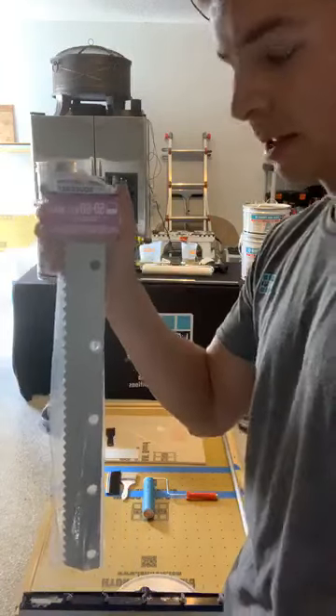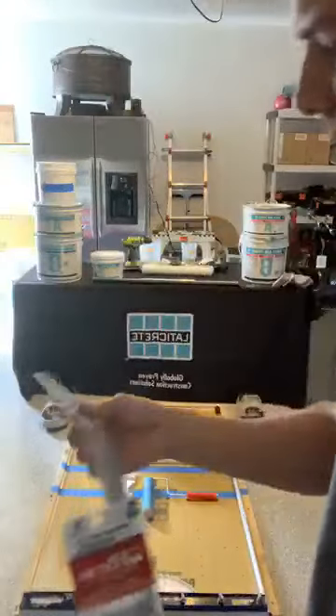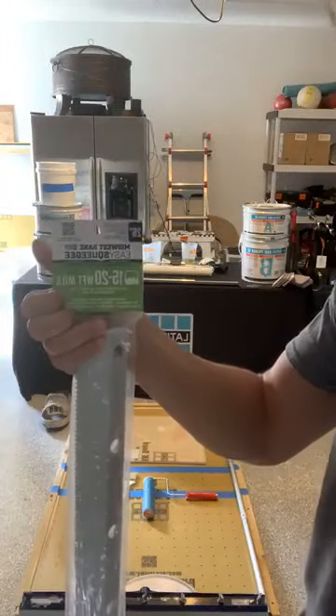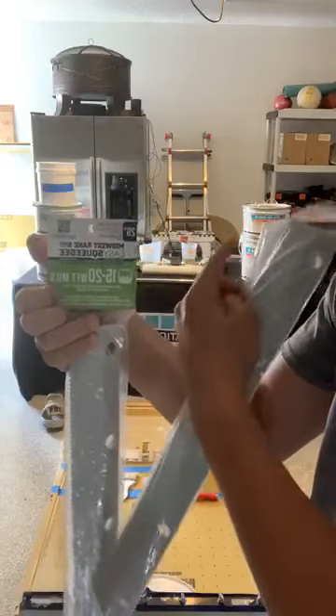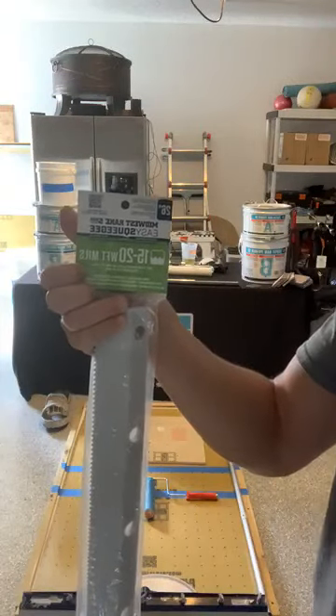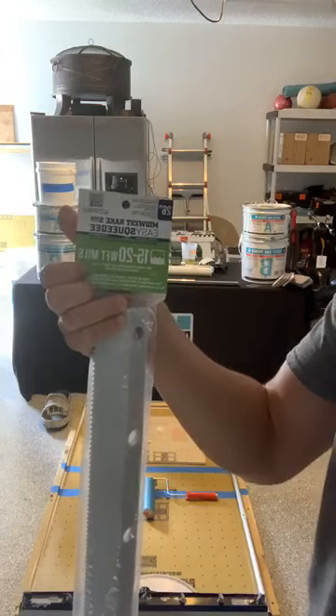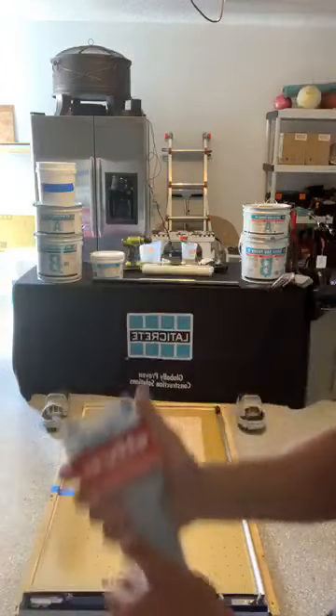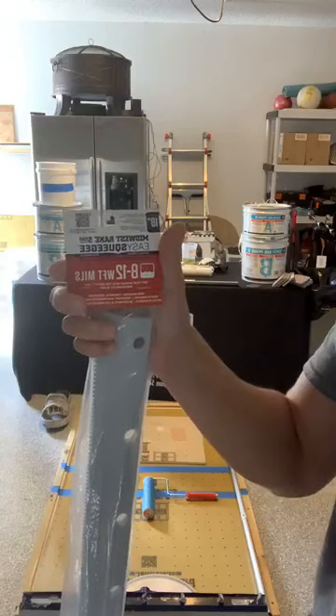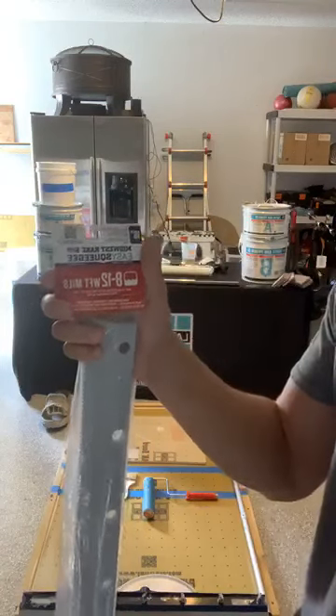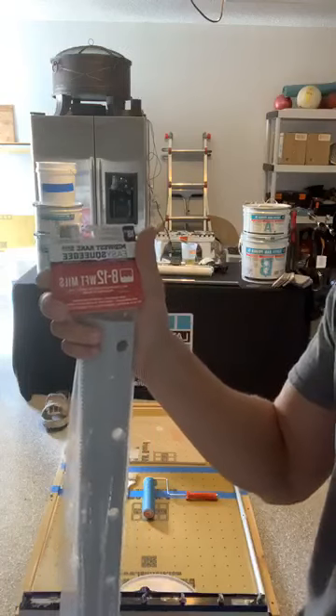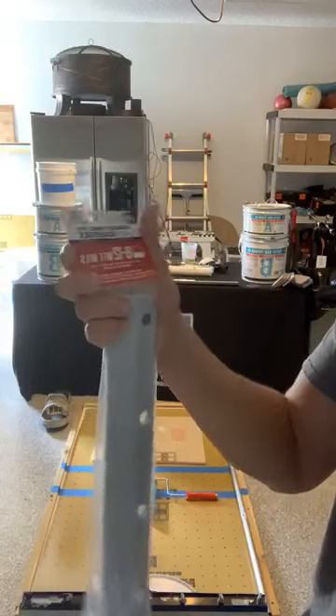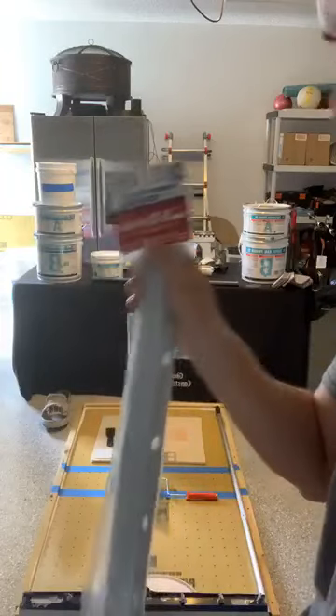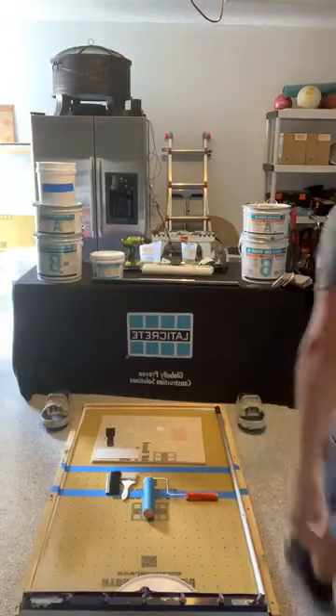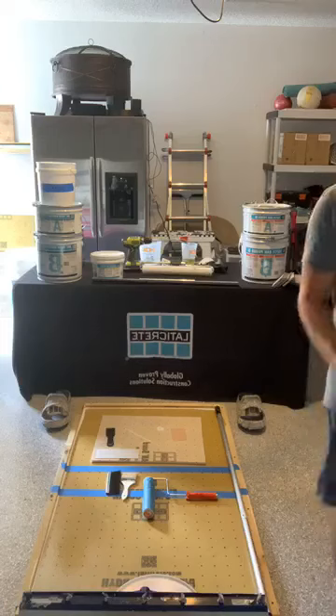So this would be ideal for almost like a metallic epoxy, a very thick material base coat. Then they have others that are 15 to 20. So this one would be ideal for vapor barrier. So I would put minimum down pressure on this, and that will get me to that 16 mil range that I need. Okay? This one, 8 to 12, would be perfect for this product, with absolutely no down pressure on it, and that'll get me to that 12 mils. But how do I know I'm actually going to get that, even though this tells me it is? You would use a mil gauge.